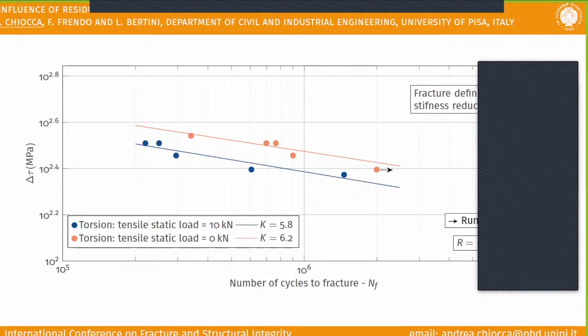Okay, I finish here. The notch specimen geometry was made to replicate in some ways the notch made from the weld seam. So the radius is the smallest possible we could design, and also the angle of the notch, to have the same plastic region compared to the welded joint. So the main conclusions here are that there is an effect made by the load, if it's pure torsion or pure loading, in presence of residual stresses or not. We are trying to understand what are the main parameters affecting this behavior, by using a simple specimen where we can control more, because usually with welding, it's really difficult to have full control of what is happening in the region of the weld seam. So thank you, everyone. If you have questions, please feel free to ask.